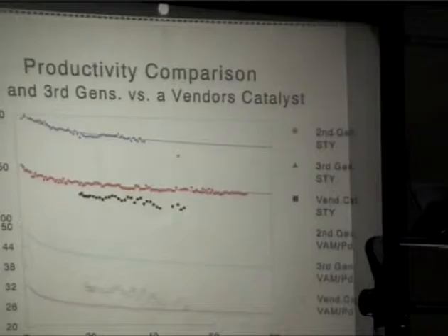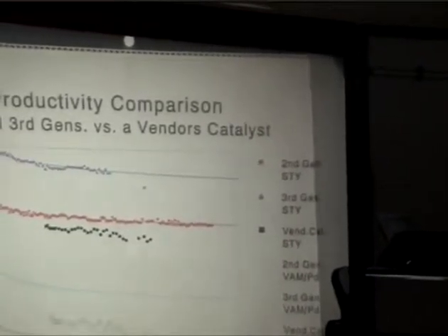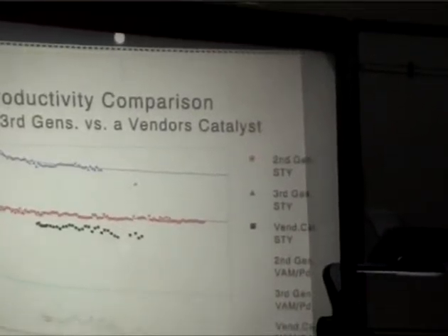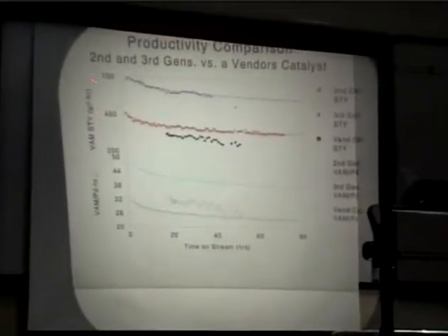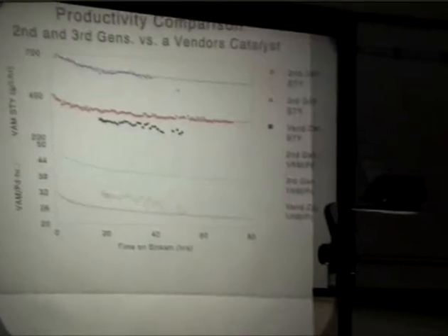Also, we wanted to see how we stacked up against other materials out there. And so we were interacting with the vendor at that point, and we said, give us your most active material and load it up with as much metal as you possibly can, because we want to see how the activity of your catalyst compares to ours. And so, again, this gives you a feel for time on stream. The top graph being a volumetric yield, space-time yield, grams produced per liter per hour. The bottom is normalized per gram of palladium.